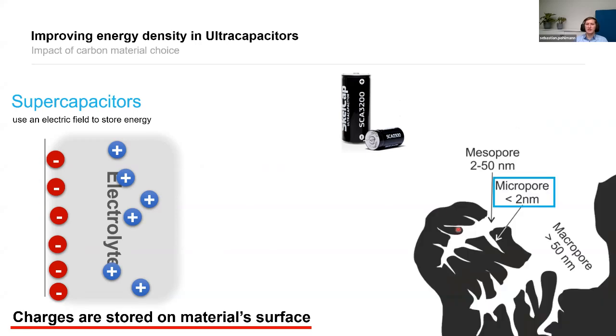In the case of activated carbon, that means they are stored in the porous structure of the carbon, and not only activated carbon, but any microporous carbon. So normally in a supercapacitor, you have some kind of carbon material which is microporous so that you have a large surface area. And we really talk here about the so-called micropores.